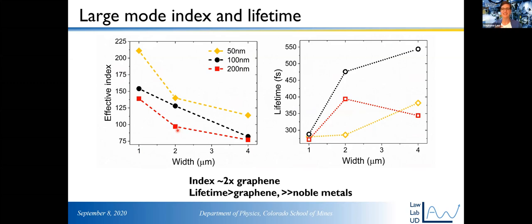Now, I want to preface this by saying these are not true lifetime measurements. We did not do a pump probe measurement. I would like to do that sometime soon. These are just looking at the full width half max, but it at least gives you an estimate of the plasmon lifetime. And using that method, we get plasmon lifetimes of 300 to 500 femtoseconds. This is better than the lifetime of plasmons in graphene measured the same way, using the full width half maximum of the excitation. And we attribute this relatively long lifetime to the fact that these electrons, as I said before, are spin momentum locked, so they can't just scatter out. They're sort of stuck in the mode that they're in.